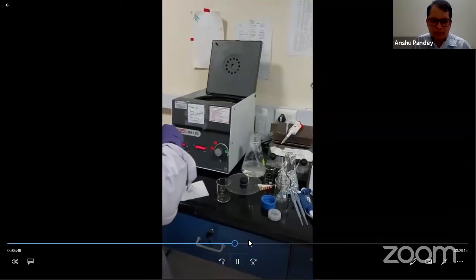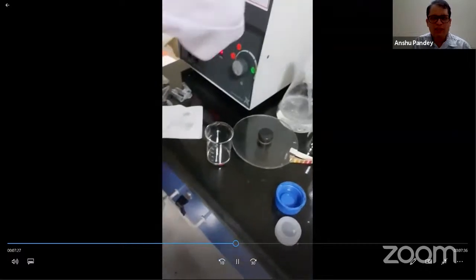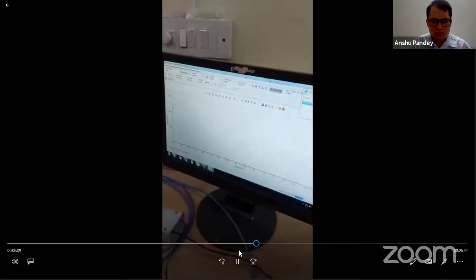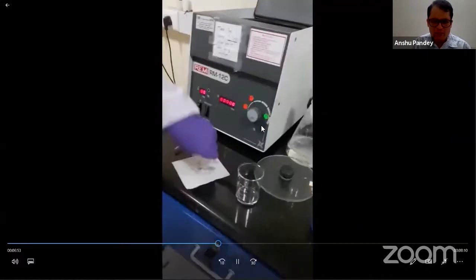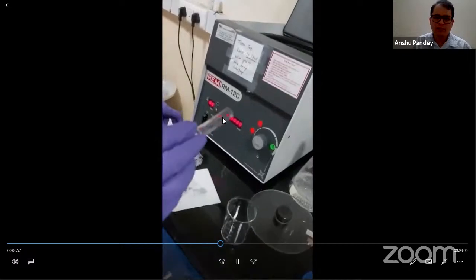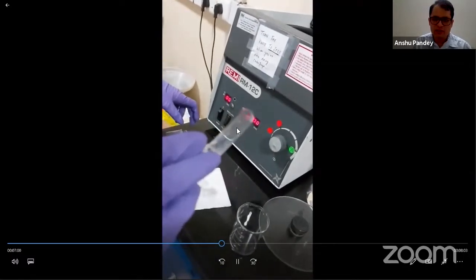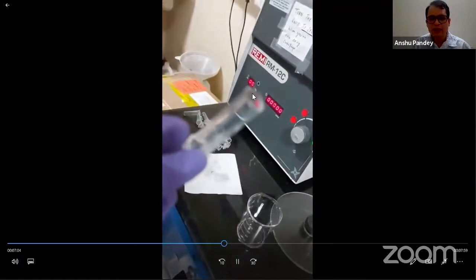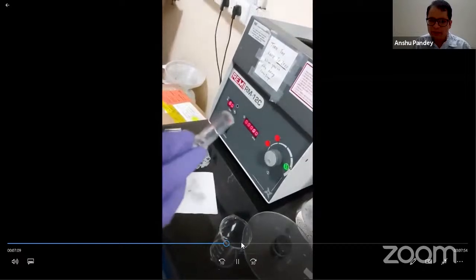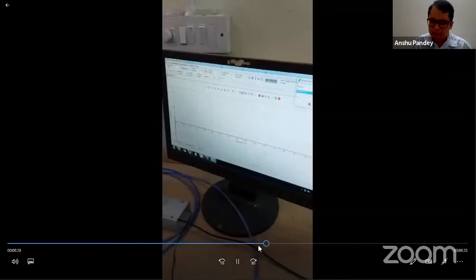which is then spun on. And once that spinning is done, which I'm skipping over again the various parts of the video, one obtains a precipitate, which sort of looks like this. So maybe I'll stop over at this part. So post-centrifugation, you find that there is in fact a black residue on each of these tubes. So this is the residue which we use for film casting. You still note that there is not the right kind of aggregation. There are still plenty of CTAB surfactants surrounding it. At this point, if we take a spectrum, we find that the material still is quite a bit lossy.